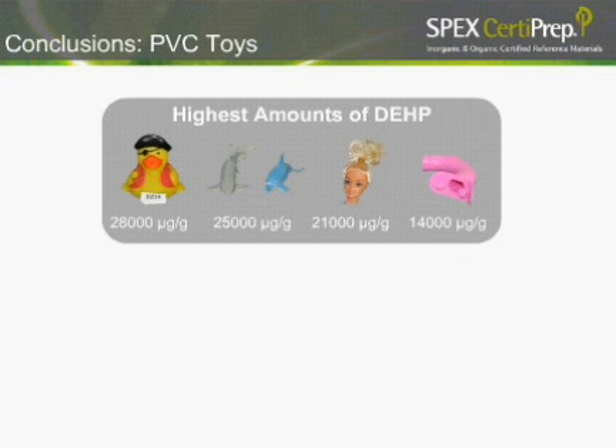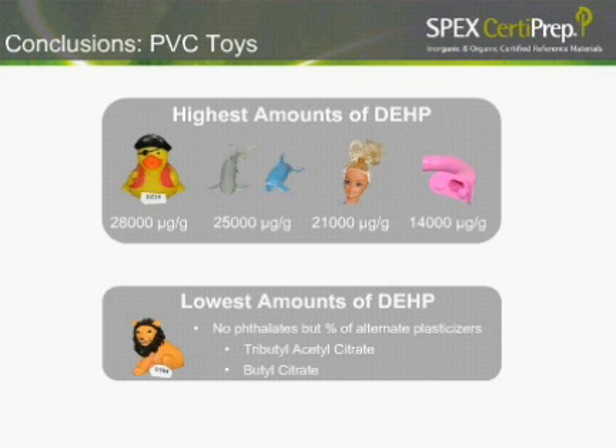The highest amounts of DEHP were in our friend the rubber duck, but we also had that snorkel mouthpiece that came in at 14,000 micrograms per gram. The lowest amount of DEHP was found in our lion, which I said had no other phthalates in it, but did have high percentage amounts of those alternate plasticizers.